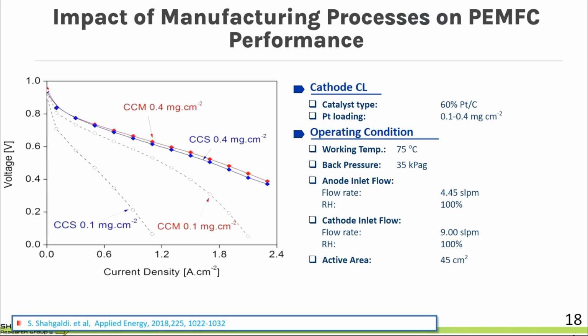So we found that if you have high catalyst loading, for example, for fuel cell, if you have 0.4 milligrams per centimeter square platinum inside the cathode, no matter if you use CCM, CCS, or decal, you will end up with the same performance. The problem is when you bring down the coating loading. When you have low loading of the platinum or iridium inside your catalyst, you cannot use CCS, because the majority of your catalyst is going to sink inside the porosity of your GDL or PTL. So definitely then you need to consider either CCM or decal method.